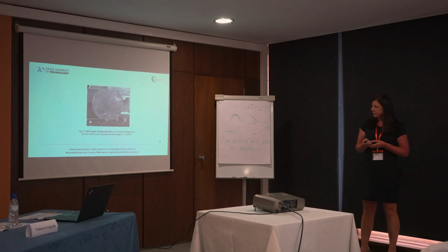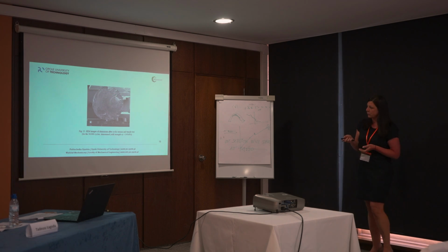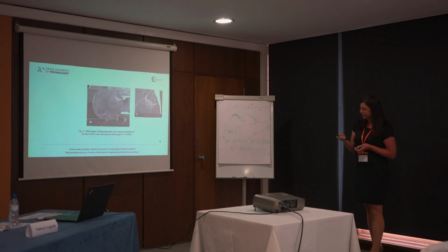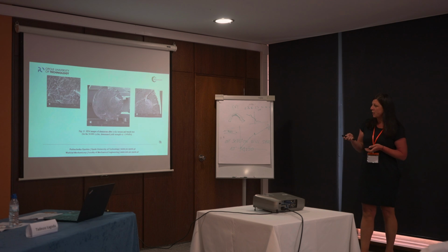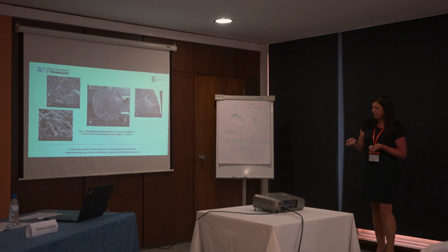In the case of aluminium, the fatigue initiation is easy to locate, and the fatigue zone is clearly marked and distinguishable from the residual zone. The fatigue initiation is accompanied by deep and numerous cracks, which are also clearly visible in the fatigue zone. And the next picture shows the area in the residual zone.